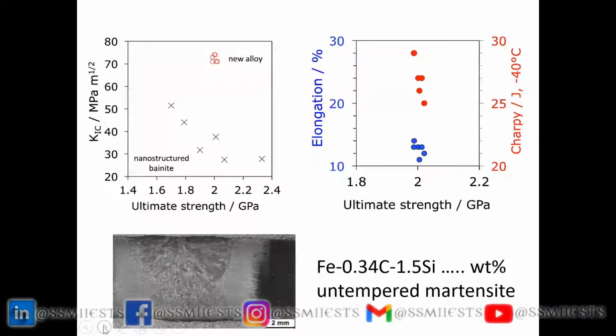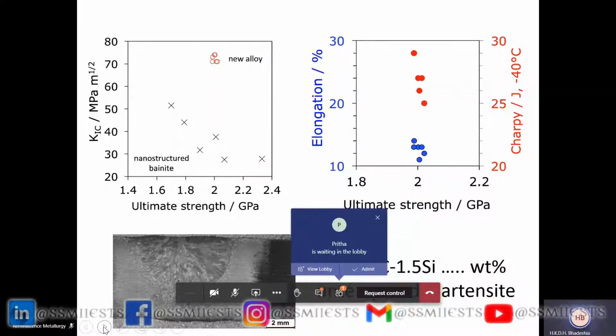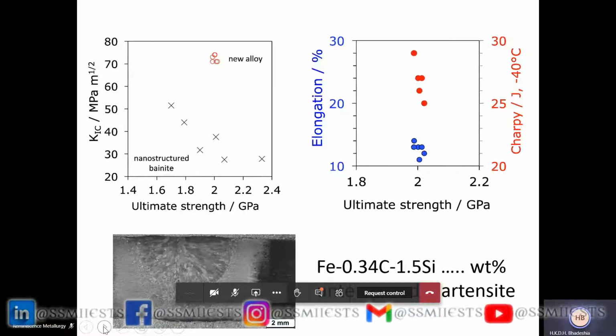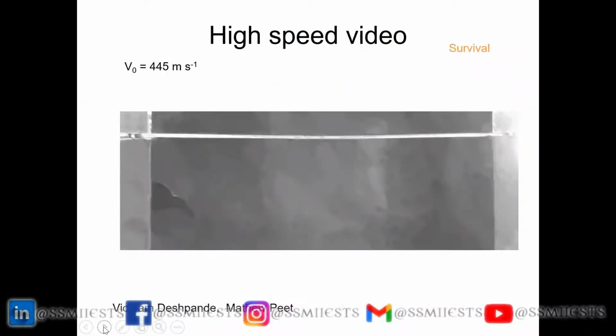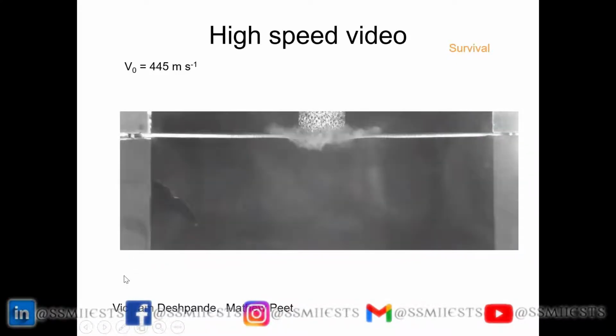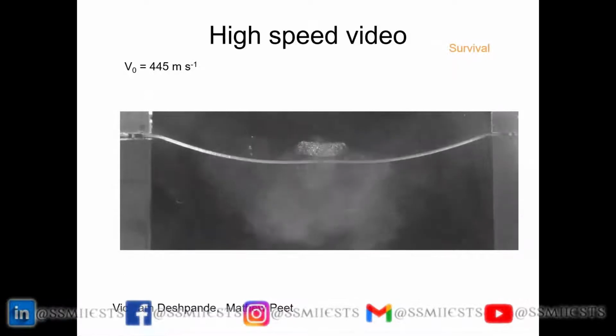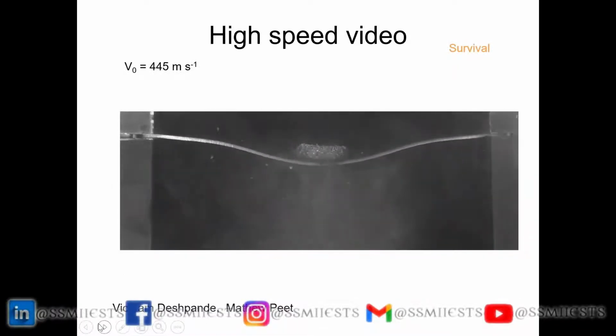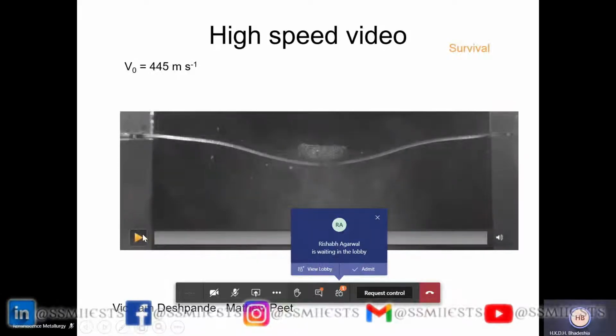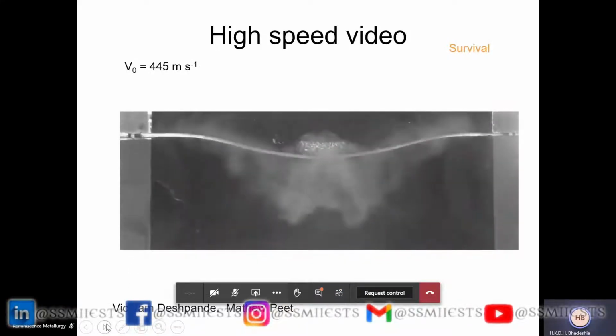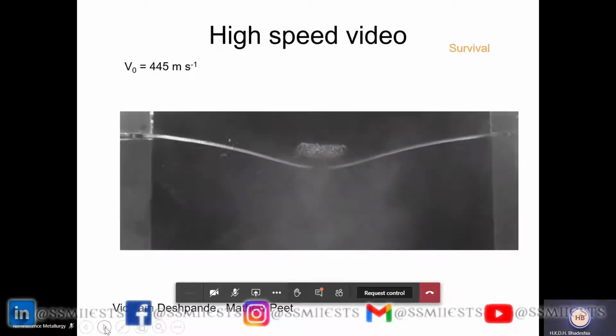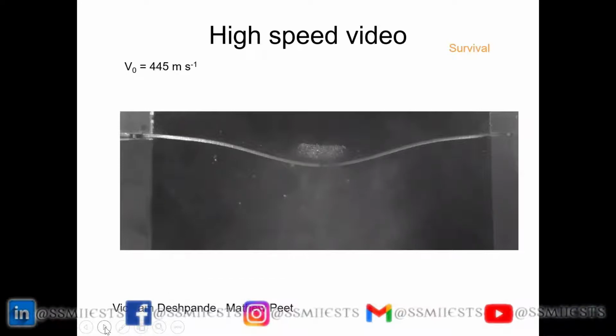Now, generally when an alloy is developed in a university, we start to make claims before they are justified, okay? So this has a strength of the order of 2 gigapascals. And one of the applications that we've been looking at is armor. So let's go to the next slide. And there is a movie there. So this armor is different. We want ballistic resistance, but we also want blast resistance. So we test this by firing at a very high speed an aluminum foil against a sheet of steel. And you can see that this steel does not break under that impact. So it can serve the dual purpose of blast resistance and ballistic resistance.